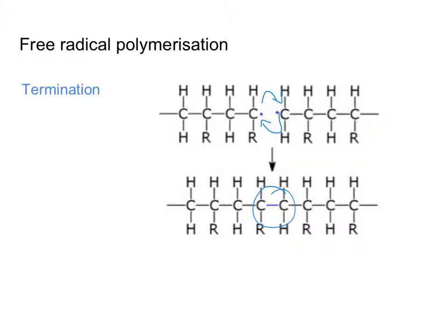Now, once again, because polymerization reactions, particularly free radical polymerization reactions, very much follow this recipe-like structure in practice, it is actually quite common at the end of a polymerization reaction for the chemists involved to dose the reaction mixture with more initiator. They spike it with a small quantity of initiator, and they do that to react any remaining growing chains.